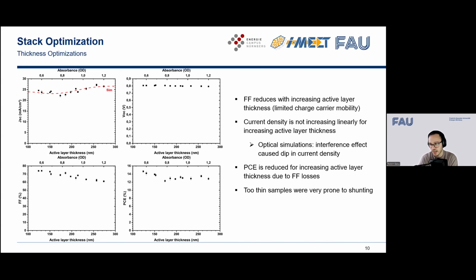So the VOC remains fairly stable. The fill factors are decreasing as expected, but what was very interesting is that we don't see a linear increase in current density. We see a dip in certain thickness ranges. And we wanted to know what is the reason for that. So we used optical simulations to check whether it's an interference effect or not. And as you can see, the simulation fits the data quite nicely. So it's really an interference effect due to the back reflecting silver electrode that actually leads to lower current densities, even though we increase the active layer thickness.